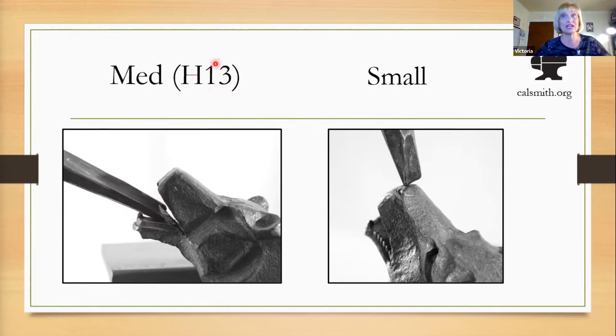However, H13, which we're recommending, or we're going to discuss here tonight, has more chromoly and another additive that makes it so that it can withstand those heat cycles, like the heating and cooling. It can be water quenched, as long as you don't let it get a color. Like, don't do that with 4140 or this: don't let it get a color and then quench it. You've totally changed the property of your steel. But H13 is designed to be thermally shocked. So that is why we're saying H13 for this particular tool.